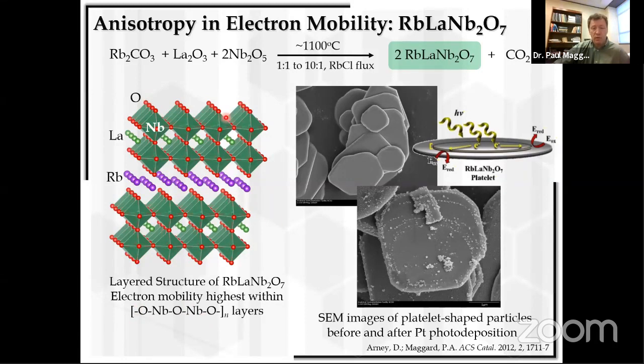So as you shine light on these particles, which crystallize out from flux synthesis as platelets here, you can basically image where the reactions are taking place by photodepositing metallic platinum onto the surfaces. Platinum 2+ is easily reduced to platinum metal by any electrons with a sufficient reduction potential. So when you shine light on these particles in the presence of a platinum salt in aqueous solution, you see those platinum islands depositing in little rings at the surface of the particle.